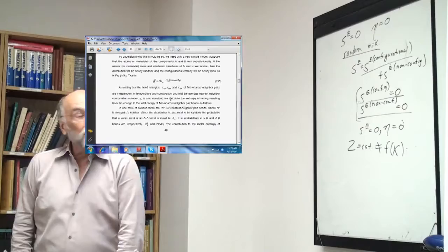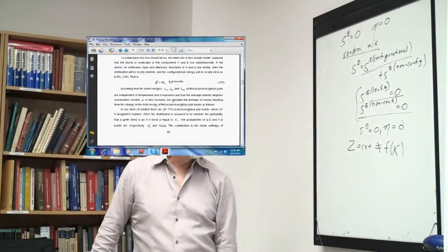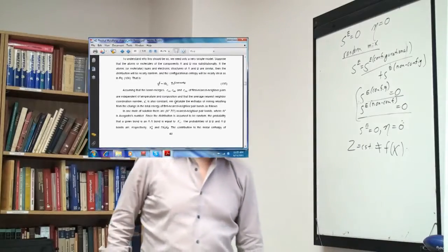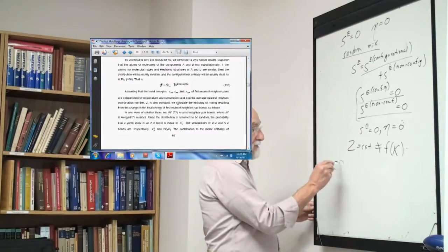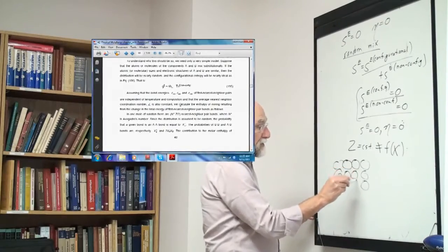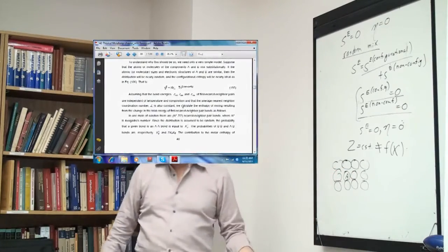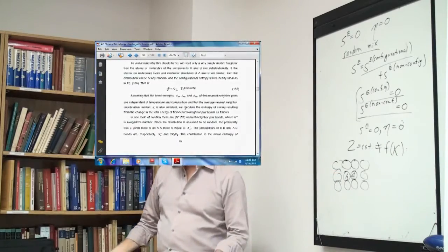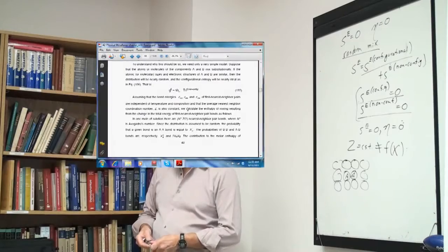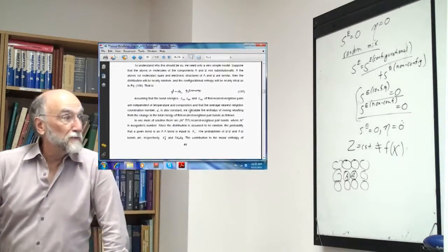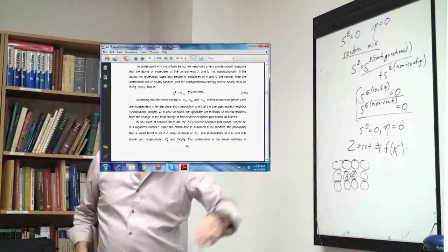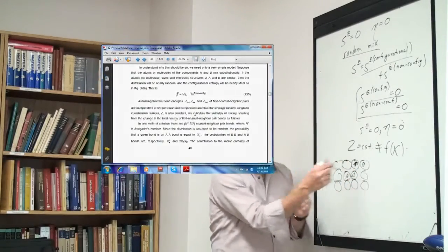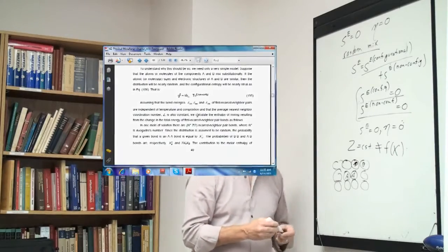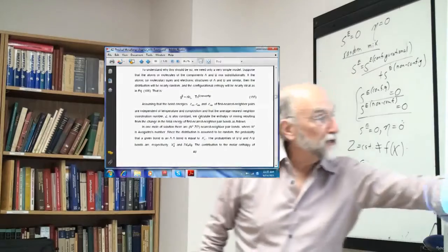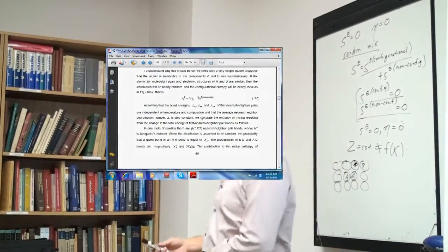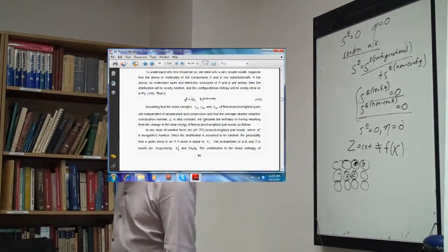And we assume that the distribution is random, that is S^XS is 0. Therefore, the probability that a given bond is an AA bond is equal to X_A squared. So I have a solution here of all my atoms lined up, and the distribution is random. The probability of an A being here is X_A. The probability of an A being here is X_A, so the probability of an AA bond is X_A squared, because it's random. The probability of a BB bond is X_B squared. The probability of an AB bond is 2 X_A X_B because you could have an AB or it could be BA. And just to check, X_A squared plus X_B squared plus 2 X_A X_B equals (X_A plus X_B) squared, which is 1.